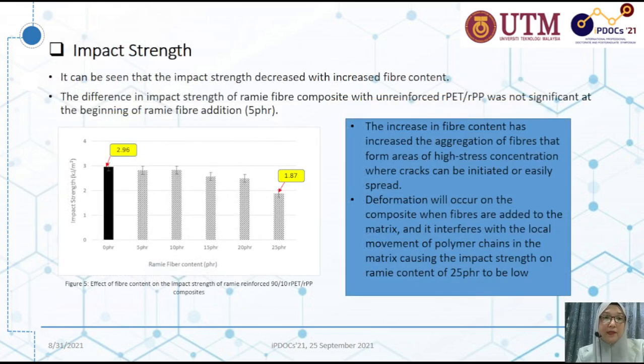Next is impact strength. It can be seen that the impact strength decreases with increase of fiber content. The difference in impact strength of Rami fiber composite with unreinforced recycled PP, recycled PET was not significant at the beginning of the Rami fiber addition, which is at 5 pHr.